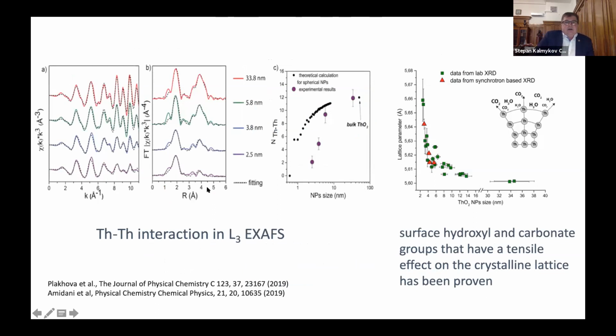The lowest spectrum is 2.5 nanometer sized particles. You can see that the thorium-thorium interaction is depressed, and while we increase the particle size to 34 nanometers, the thorium-thorium interaction increases. The coordination number in this nano region, from 2 to 10 nanometers in size, is changing. With the increase of the particle size, we have an increase of the thorium-thorium interaction and an increase of the coordination number of thorium.